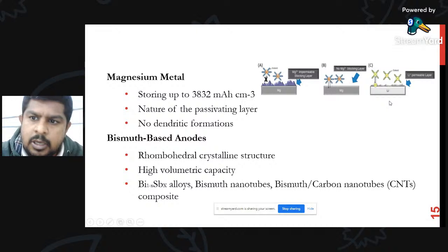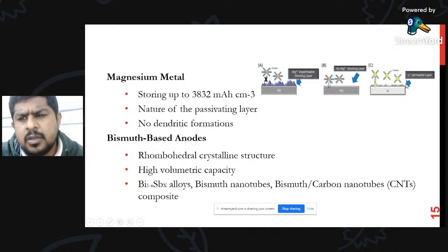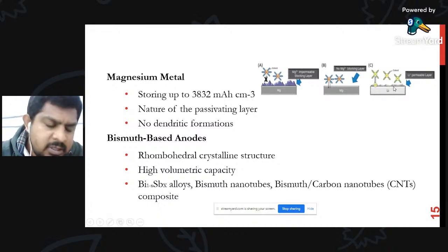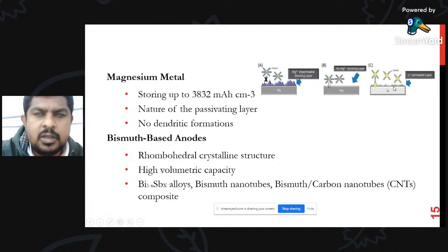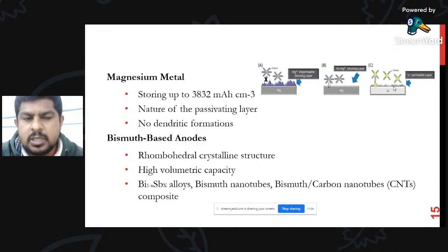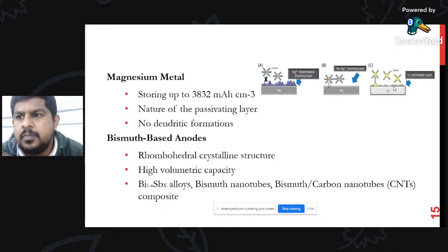But in a lithium ion, even if you're using those electrolytes, there is also a possibility of forming these passive layers, the SEI layers, and there will be short circuits. The main thing is the lifetime of a battery will decrease. The storing capacity is getting faded, gradually reduced after a long time.